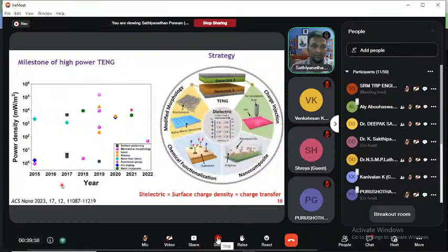After the invention, in the beginning of 2012, because they accidentally discovered this thing, they then tried to improve the energy harvesting performance of these triboelectric devices. So they came up with different strategies. For example, modifying the morphology. Morphology plays a very important role. Also modifying the chemical functionalization, doing functionalization on the substrate of any positive or negative material. You can introduce many negative groups or positive groups or some ionic groups, so that you can tune the surface charge density. Similarly, you can incorporate some nanoparticles into the polymer matrix, and you can improve the dielectric constant of the material, so that it will improve the performance. Similarly, charge injection process.